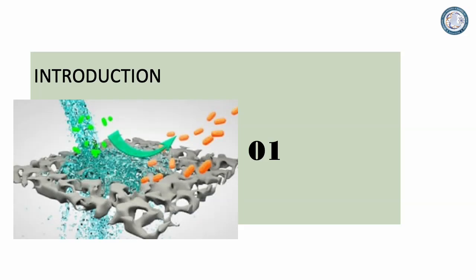plant extract-based green synthesis. The reduction and formation of the nanoparticles was monitored through FTIR spectroscopy, which was also carried out to identify the functional groups of biosynthesized cerium oxide nanoparticles. The size and zeta potential values indicated the biosynthesized nanoparticle stability and surface charge features. The morphology, the shape, and the size of the nanoparticles were analyzed in the transmission electron microscope and scanning electron microscope. The crystalline nature of the nanoparticle was analyzed in an X-ray diffractometer. Additionally, the antioxidant activities of the nanoparticles were evaluated by the scavenging capability of DPPH free radicals.